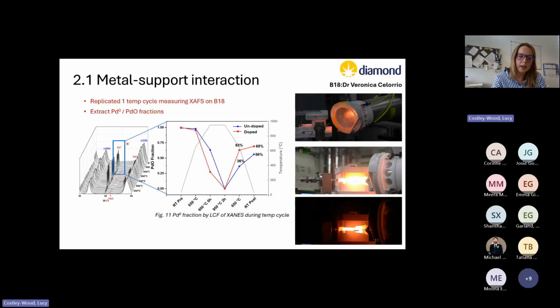So this is just one of our temperature cycles in the powder diffraction using X-ray absorption spectroscopy. And this was on B18 with Veronica as our local contact. So we started with 100% palladium oxide at room temperature. We increased the temperature through 650 up to 950 degrees, waited 2 hours as we did in our XRD cycling, and then cooled it back down. We start to achieve palladium metal as we expect by the 950 mark, and after 2 hours we have fully palladium metal, which then reoxidizes during the cooling.